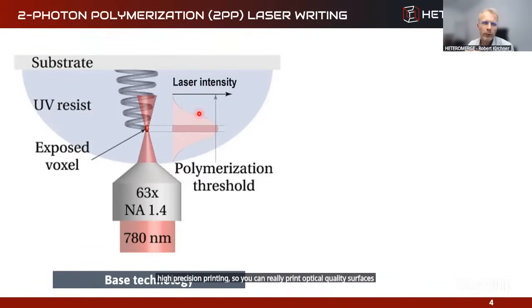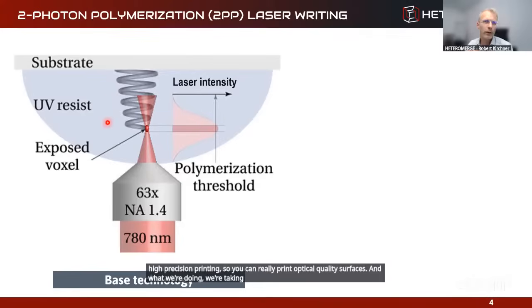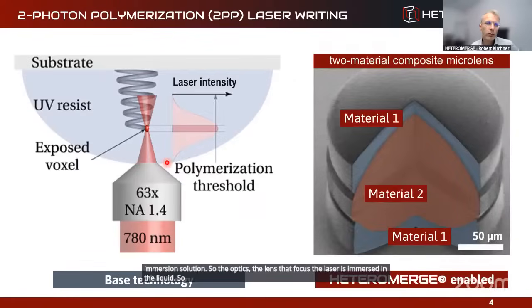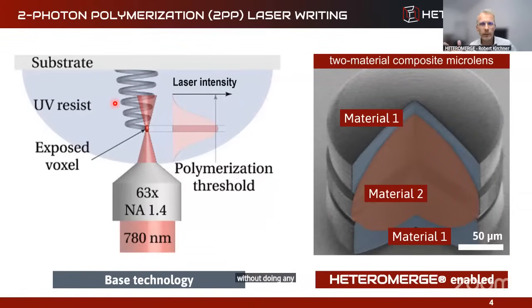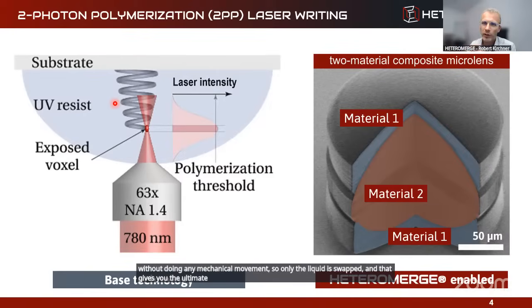And what we're doing, we're taking this immersion lithography. At the end, it's an immersion solution. So the optics, the lens that focuses the laser, is immersed in the liquid. What we are doing is swapping the liquid without doing any mechanical movement. So only the liquid is swapped, and that gives you the ultimate alignment precision. We come to that a bit later. But what you get is having one material.